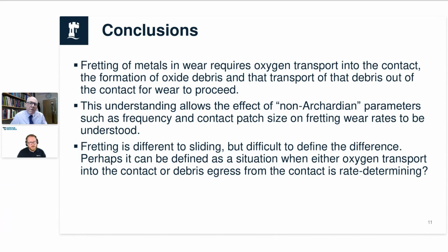It's very difficult for debris transport, and sometimes the wear rates look tiny and you think, oh well, this isn't too bad, and then you look subsurface and there's cracks everywhere. So then the fretting fatigue people become terribly upset, and rightly so. So it tends to lead towards a much more damaged structure within the metal itself.